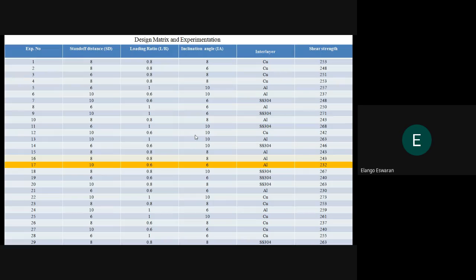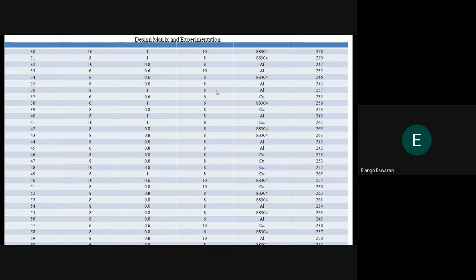This slide shows the consolidated shear strength of different interlayered aluminum steel explosive clad corresponding to experimental conditions. As per the 4-factor 3-level orthogonal array, we conducted 60 experiments.